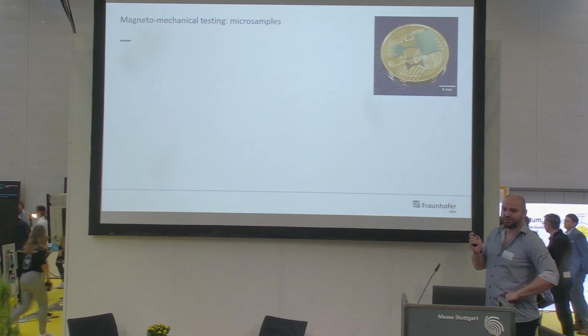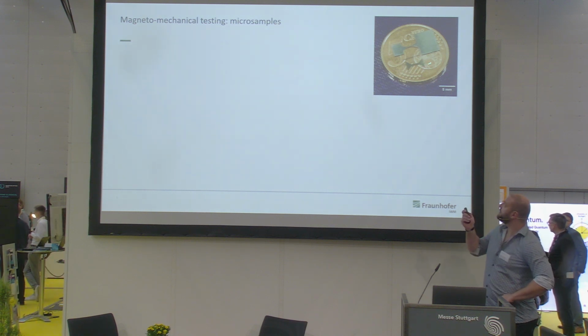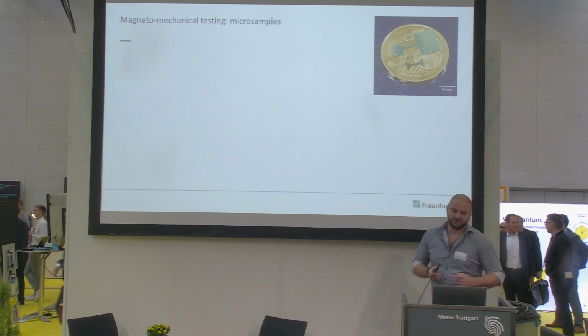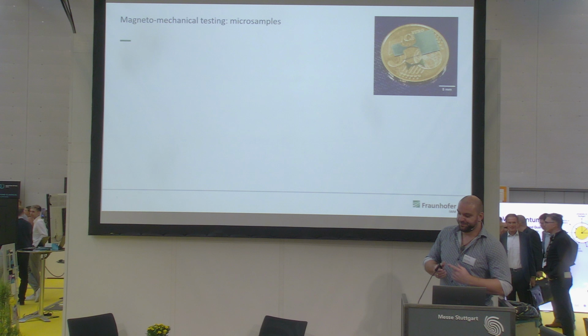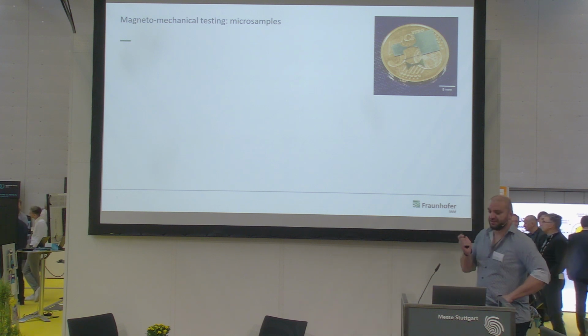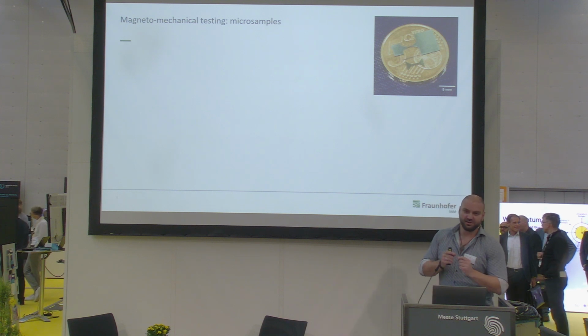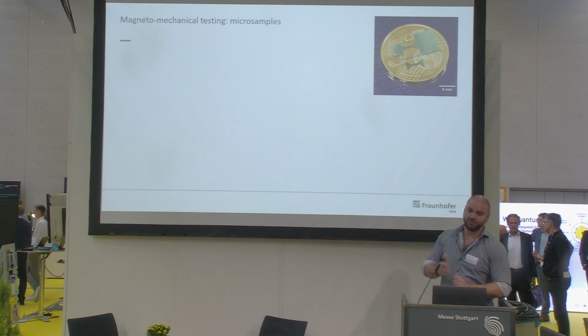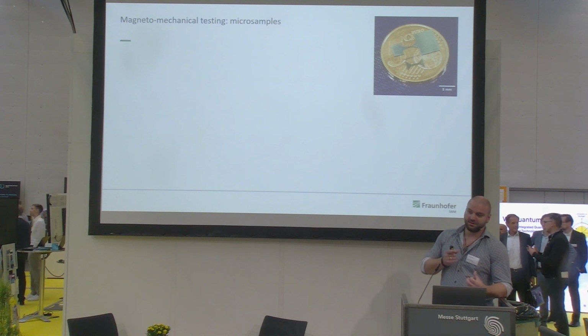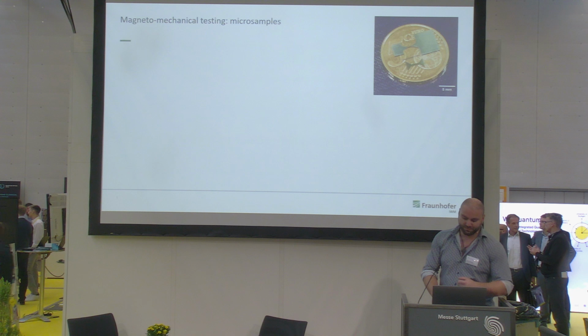As you can see here, this is a typical tensile test sample that we use. It all fits on a very small coin. This holds a certain advantage, namely the volume of these small tensile test samples is so small that we are in the region of a technical crack, which means if this thing breaks, it breaks at exactly one point. This gives us the opportunity to have a high degree of control, and we can compare many experiments with each other because we only have one damage point.